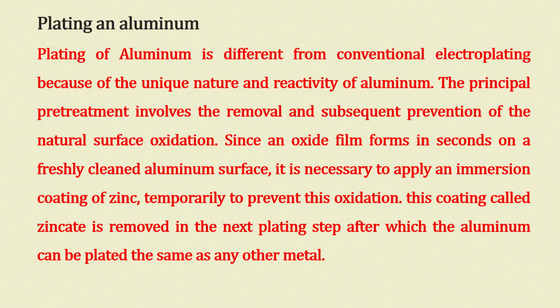So, now we talk of plating on aluminum, not coatings, not anodization, plating. Plating of aluminum is different from conventional electroplating because of the unique nature and reactivity of aluminum. The principal pre-treatment is the removal and subsequent prevention of the natural surface oxidation. Oxide film normally forms within seconds on a freshly cleaned aluminum surface. So, it is necessary to apply an immersion coating of zinc temporarily to prevent this oxidation. It is called a zincate, a sodium zincate, aluminum zincate, and that is removed in the next plating step, after which aluminum can be plated like any other material.